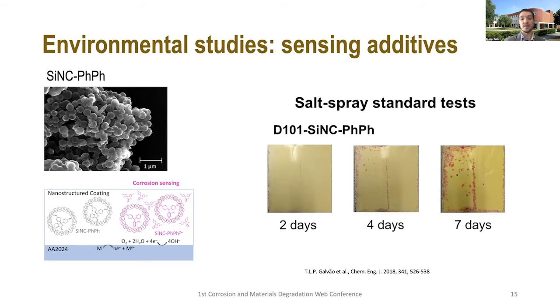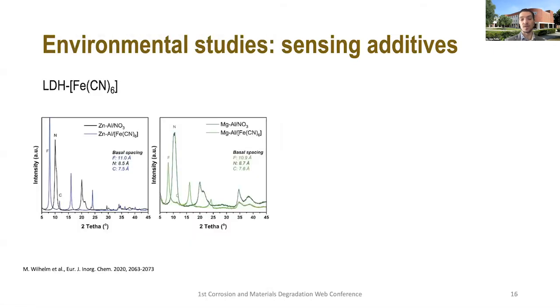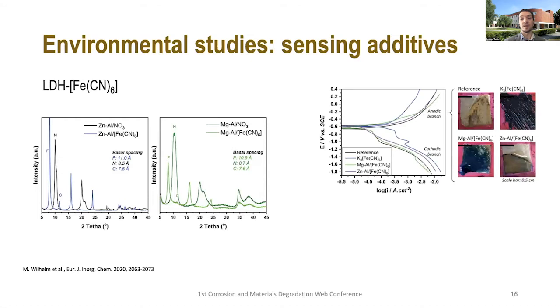Another type of additive that we were also considering was developed more recently. We intercalated hexacyanoferrate, and in this case, the idea was the intercalation of hexacyanoferrate in LDH and control of the release of hexacyanoferrate in the presence of chlorides. And we could see that indeed the released hexacyanoferrate would then react with the iron cations from the anodic reaction and form the well-known blue pigment, Prussian blue.